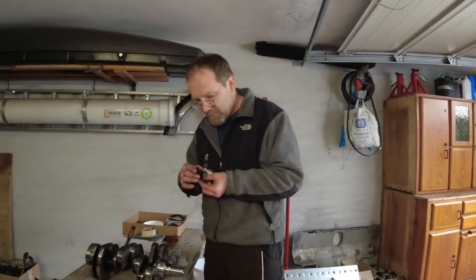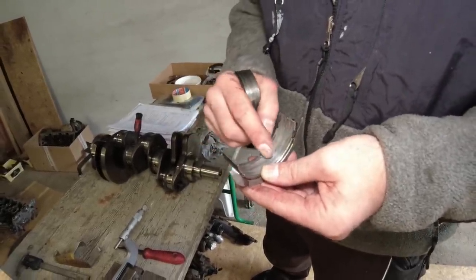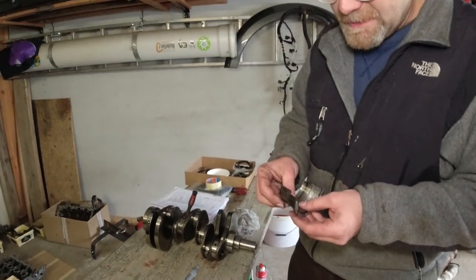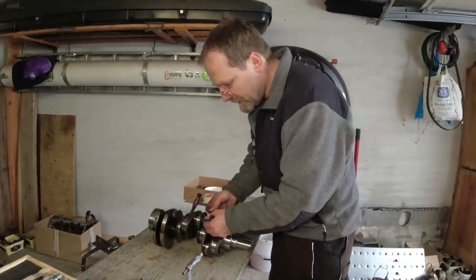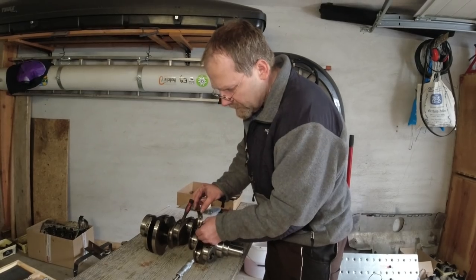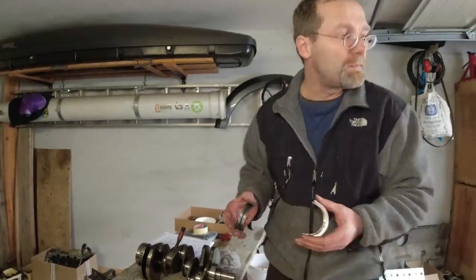This delamination - by prolonged cranking, wrong oil, bad oil, contaminated oil, wrong bearing clearances, or bad luck from the guy who assembled it in the plant - can void those bearings. They will start to delaminate and chips will come off. These chips will collect and get into the oil pump. The first chip or debris causes a chain reaction, creating more debris. It gets the first rubbing marks, and eventually these chips will put so much force on the bearings that they start to turn in the engine block. Then your engine dies within minutes.